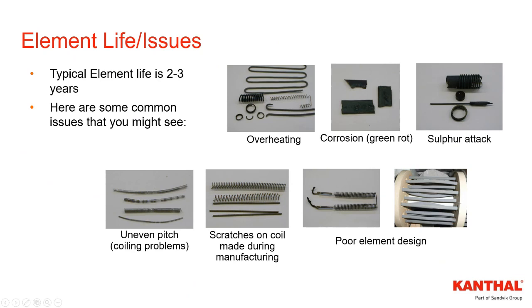Here at Kanthal, we can assist on conducting investigations on causes of element failures and can make recommendations based on that investigation. So you might have overheating, corrosion. This is green rot. It's specific with nickel chrome alloys. Might have sulfur attack, so it's maybe something from the process or your atmosphere. Again, uneven pitch of coiled elements, so it might be from elements sticking to the refractories. You can get scratches on the coil during manufacturing or during installation, so it exposes some of the base material.